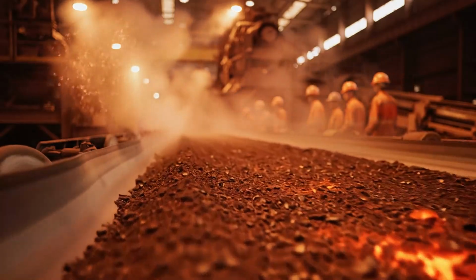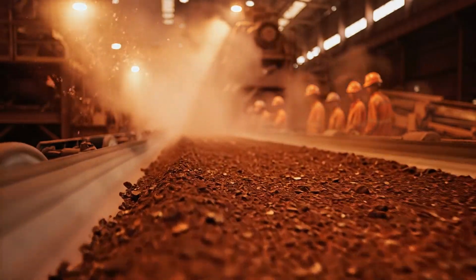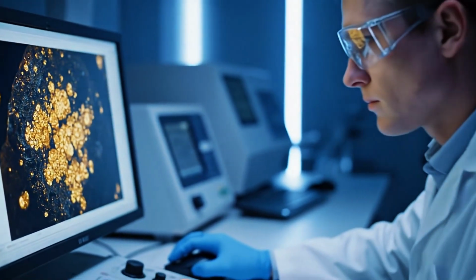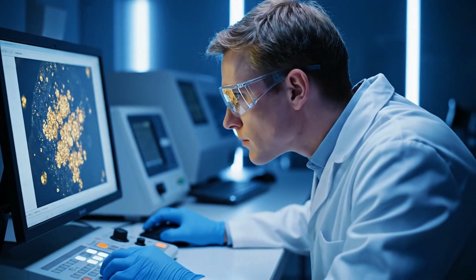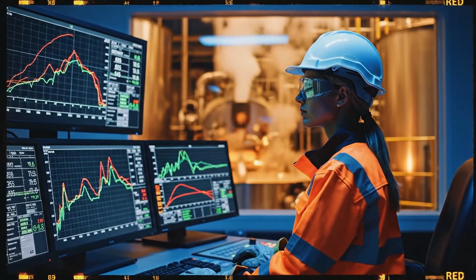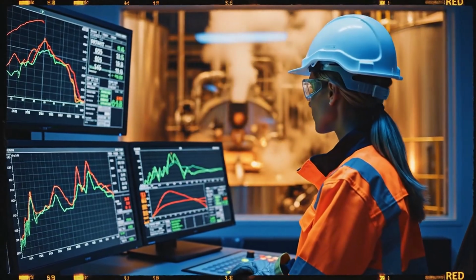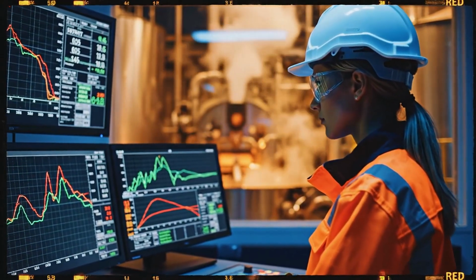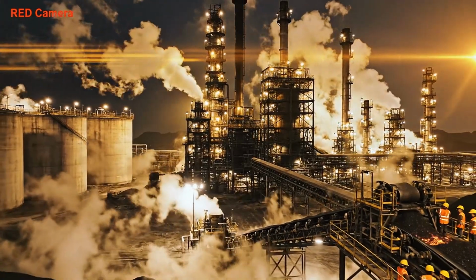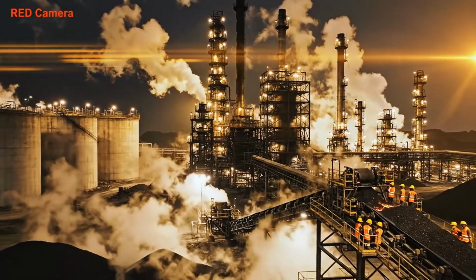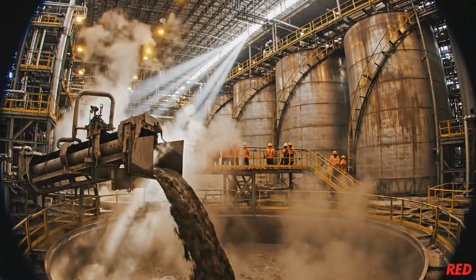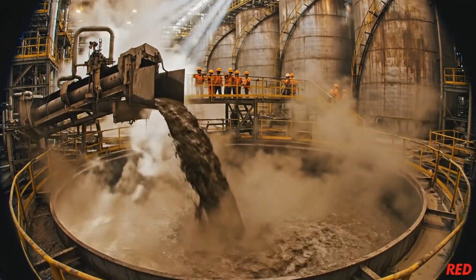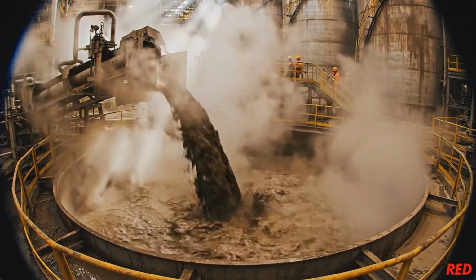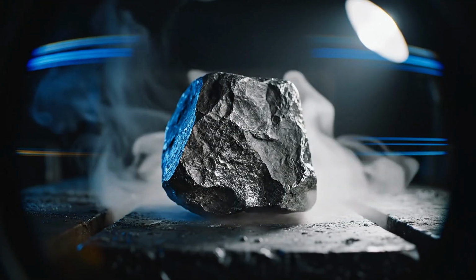The roasted ore emerges as a fine, reddish powder that's been fundamentally transformed at the molecular level. What was once locked gold is now accessible, but the process requires precise temperature control and sophisticated emission control systems. A single roaster processes 500 tons of concentrate daily, while producing enough sulfuric acid to supply a medium-sized chemical plant. The roasted ore enters the most chemically intensive phase of gold extraction, and sodium cyanide solution, heavily diluted but still requiring extreme safety protocols, is mixed with the ore in massive tanks called leach vessels.